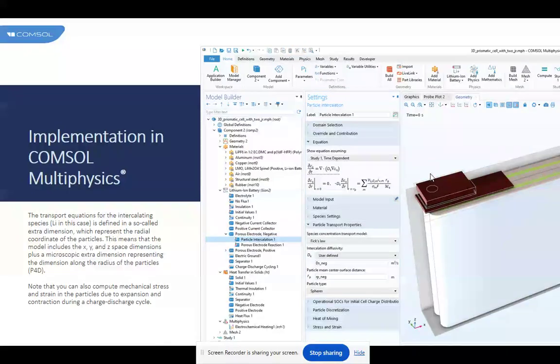The transport equations for intercalating species in this case are defined with a so-called extra dimension, which represents the radial coordinate of the particles. This means that the model includes the x, y, and z space dimensions plus a microscopic extra dimension representing the dimension along the radius of the particle, which is a fourth dimension. Note that you can also compute mechanical stress and strain in the particles due to the expansion and contraction during a charge-discharge cycle.